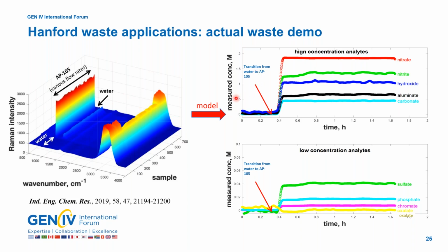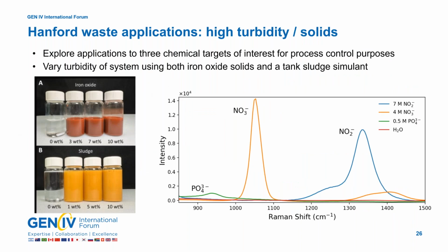And this shows the concentration on the y-axis versus time through the process. We start with water at the very beginning, then we transition to AP105 waste about half an hour into the process. And the top plot here shows the concentration of the high concentration analytes, showing nitrate, nitrite, hydroxide, aluminate, and carbonate. The bottom plot shows, for convenience, the lower concentration species, sulfate, phosphate, chromate, and oxalate. So we can follow the concentration in real time for 9 analytes simultaneously throughout this process. And this is actual waste which has not been conditioned any special way before analysis. And the next slide shows,